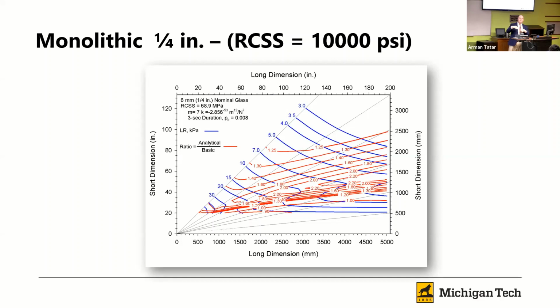Because that's what we're doing. So we know just by the way stuff is manufactured that the glass is going to be a little stronger because it's going to be manufactured at a higher RCSS. Well, the previous standard, the basic method, didn't address that at all. It just said, doesn't matter what it is, it's 2. And then magically, when we get to 10,000, now it's 4, okay? So one would say, well, there should have been at least some gradient between those two. In reality, there is. Our standard, or the analytical method, has the capacity to analyze glass with respect to that. But again, we've kind of chopped it off to the minimums for design usage.